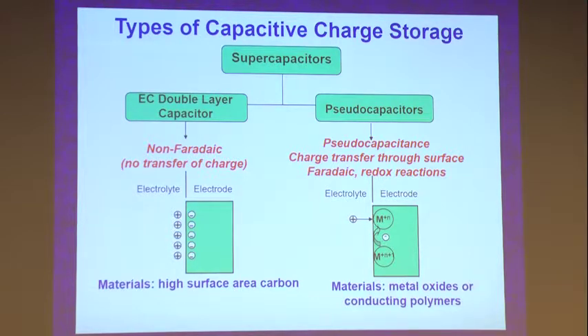What we are going to talk about today is something called a pseudocapacitor. And pseudo is now the active word, because the distinction between a battery and a pseudocapacitor is much less clear. So what does this system consist of? For cathodes, it's a transition metal oxide that is the exact same material as a battery material. And in that pseudocapacitor, we are going to do the exact same redox chemistry that we do in a traditional battery. That is, we might do redox on a transition metal, take a lithium ion, make a tight ion pair with that reduced transition metal in the exact same way that you do in a battery. But we're going to do that at the surface or in the near surface regime of a material. And so as a surface phenomena, it becomes similar to a double layer capacitor, but it is a redox-based system.